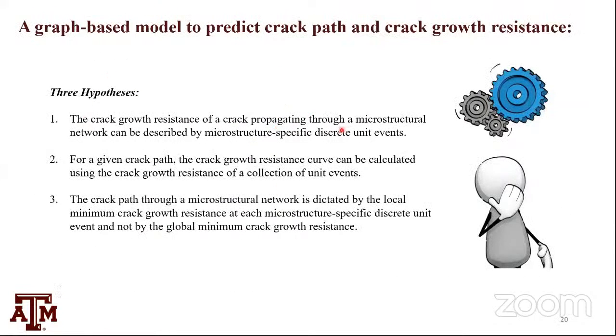So my crack growth resistance through a microstructure network can be described by microstructure-specific discrete unit events, at least in the circumstances where I know what feature the crack is following. And for a given crack path, the crack growth resistance curve can be calculated using the crack growth resistance of a collection of unit events. This is what we believe as material scientists or engineers. This is what I just showed you is possible if I know.